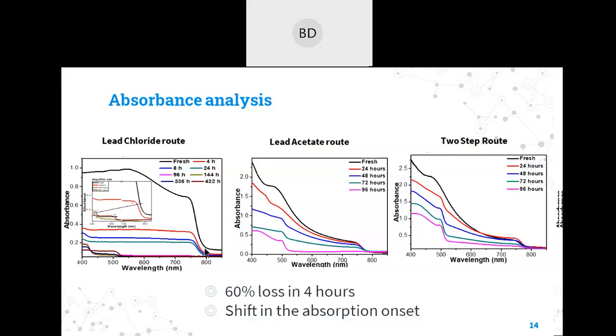The second observation here is, if you see in this magnified image, there is a shift in the absorption edge. When you are aging it for some time, with the aging time, there is a shift in the absorption. Up to 24 hours, it shows some kind of perovskite phase, but after 24 hours, the absorption onset goes to around 450 nanometers. Then, for prolonged aging, this absorption edge shifted to around 500 nanometers. But in the case of the lead acetate route and the two-step route, the absorption edge is at around 500 nanometers in both cases, and it takes a lot of time to degrade. So this was some difference in the absorption analysis that we have got for the lead chloride route.